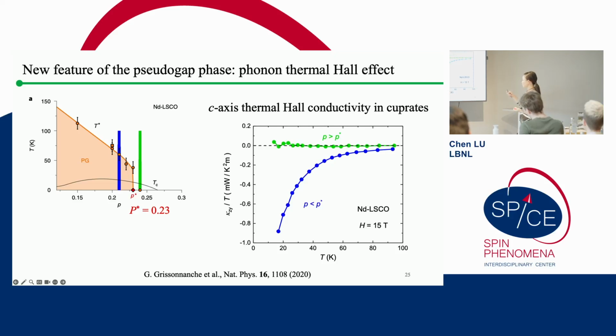So how do we do that? We basically measure something called the c-axis thermal Hall conductivity. As I showed you in the introduction, you always need to put a field and a current direction along certain principal axes of your material, right? And here, for the c-axis thermal Hall conductivity measurement, we apply the heat perpendicular to the copper oxide plane.